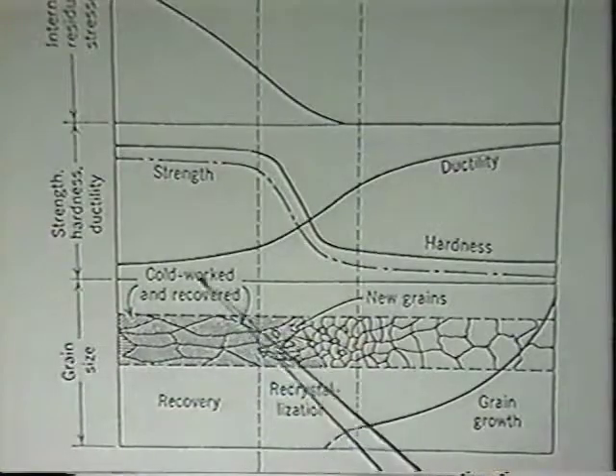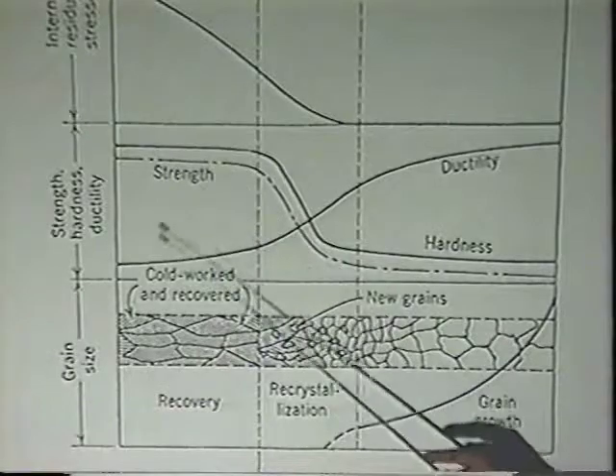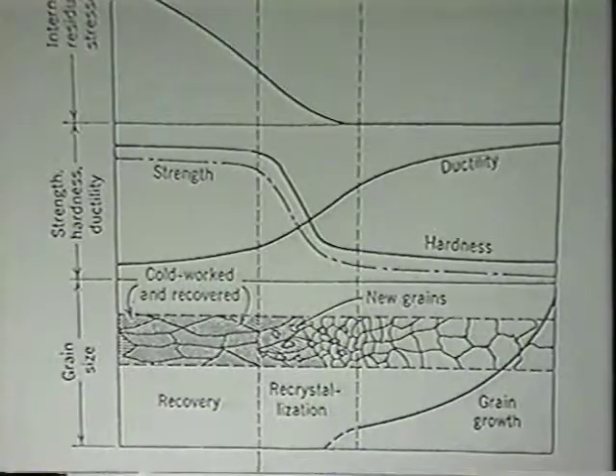We sell a product called stress relief anneal. 80,000 yield, 90,000 yield type products go through nothing more than this very front end of the anneal cycle, where we remove some of the stresses to get a little more ductility out of it, but without any loss of strength. So if you hear the term stress relief anneal, that's all it is. Taken up to about 1,000 degrees. No real change in the crystalline structure, just some changes in the internal residual stresses to give yourself a little more stretchability or ductility without a loss of strength.